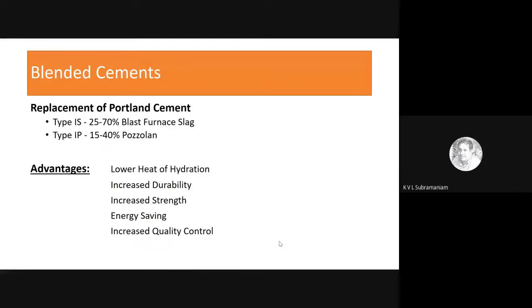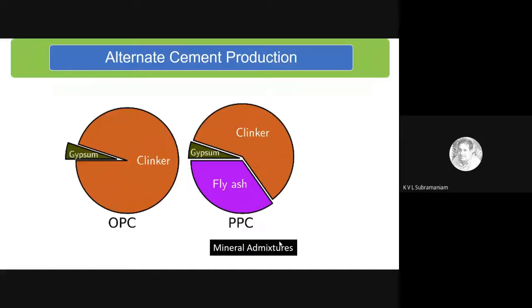So with these blended cements, then we basically have replacement of cement with blast furnace slag and or fly ash, and basically we are relying on the pozzolanic activity. And these blended cements are now commercially available. They have several advantages, which include lower heat of hydration, increased durability, increased strength. These are all now known and have been established. And this is a typical replacement chart with fly ash, where we are stuck at 35%. And of course, with slag, we can go up to 70%.